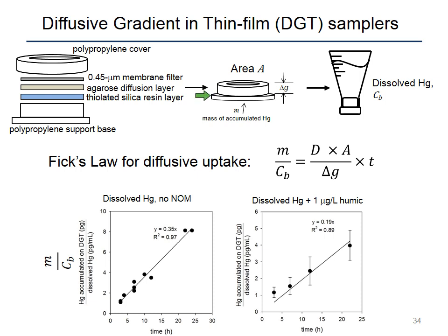You deploy this in either the water column or sediments. And what happens is that the dissolved phase of the mercury penetrates from the top of the filter, diffuses through the diffusion layer, and then binds to the thiolated resin layer, which acts like a perfect sink for mercury. So the way people have deployed these passive samplers is assuming that the uptake of mercury or metal on these DGT samplers occurs through Fick's law for diffusive uptake, so assuming that you have only dissolved species.